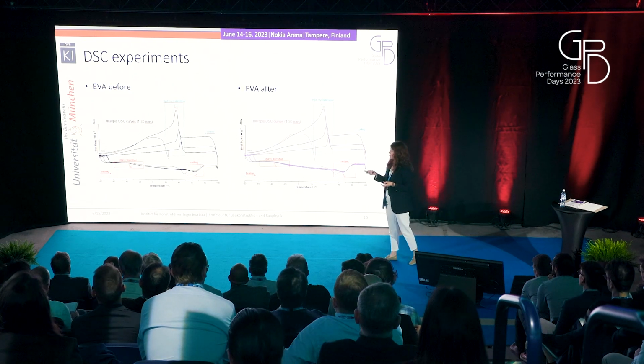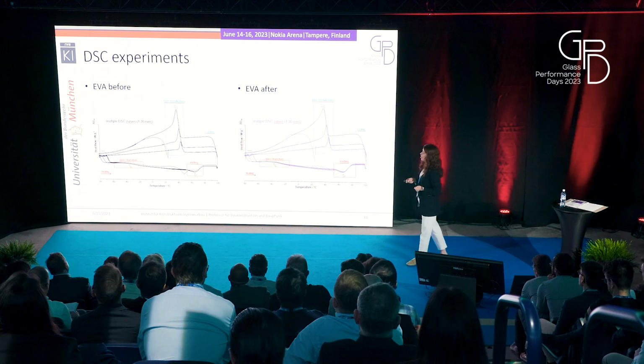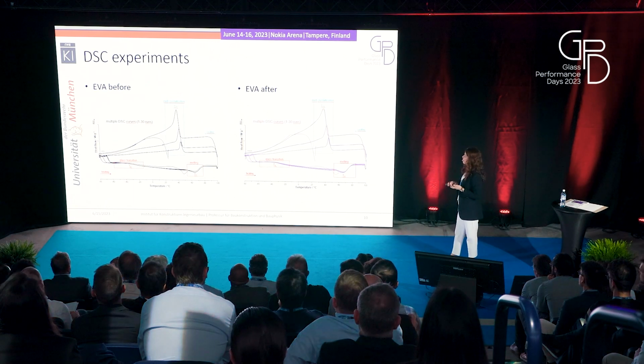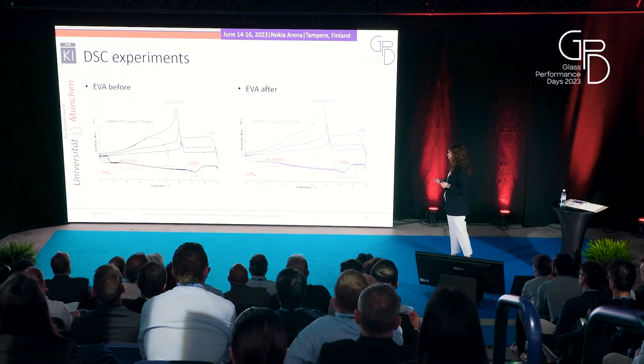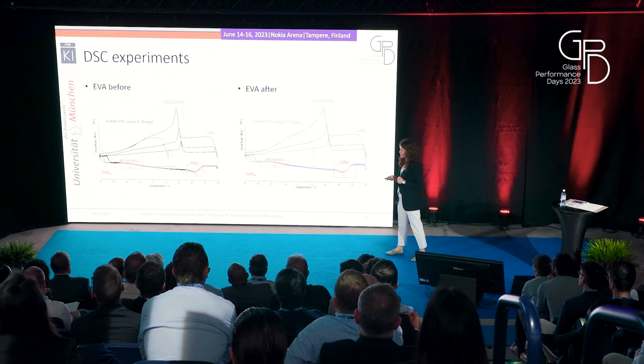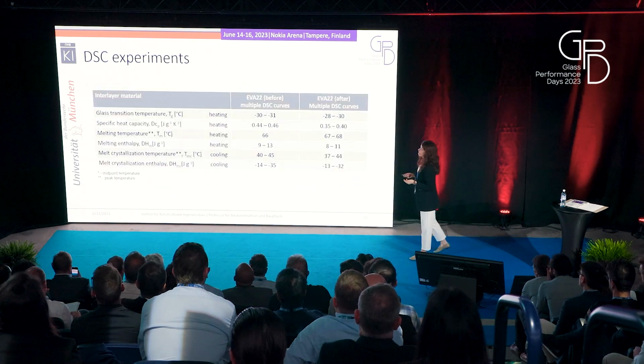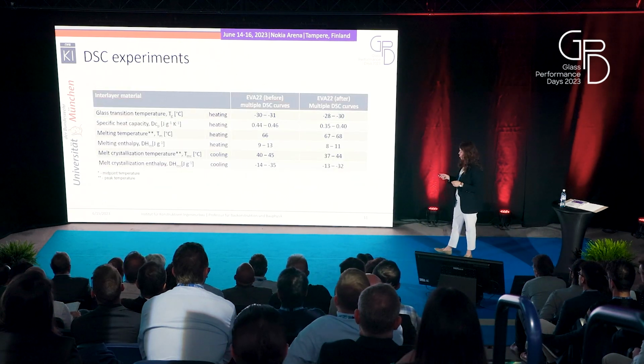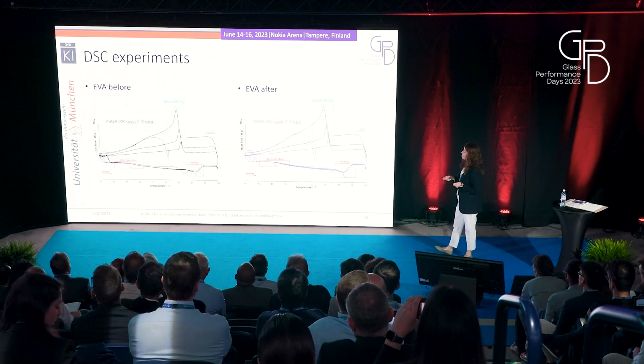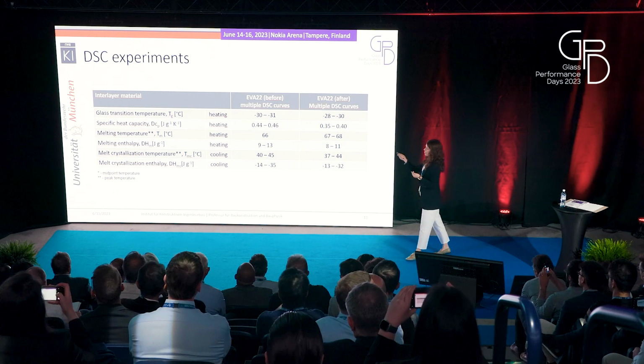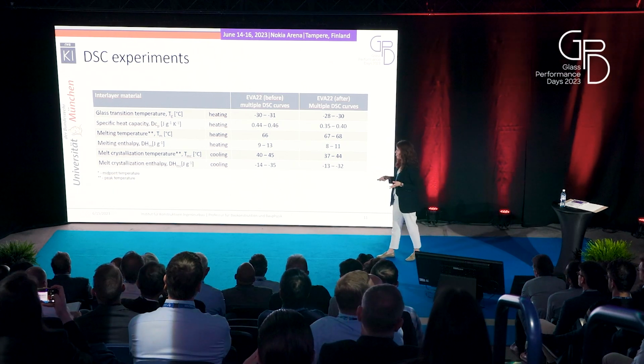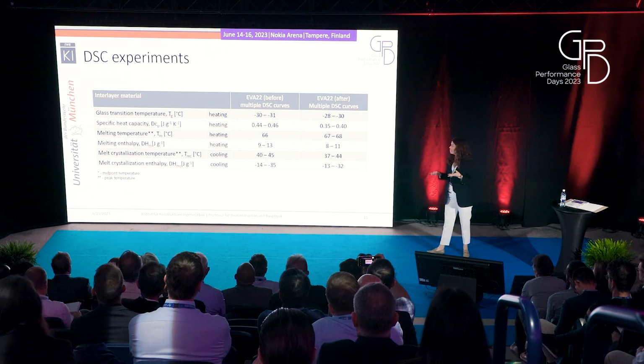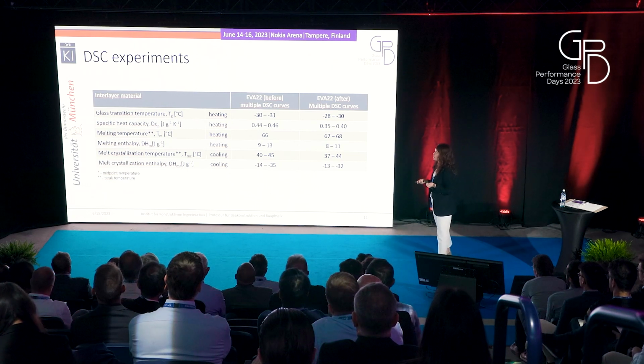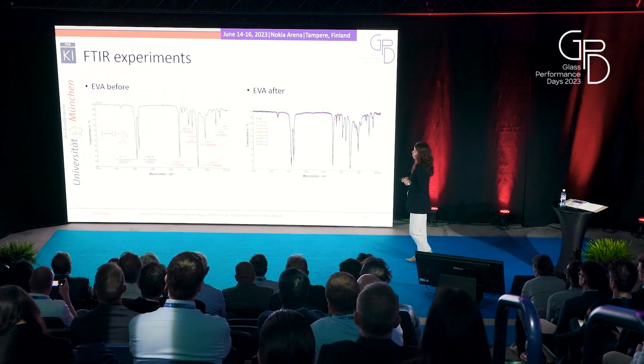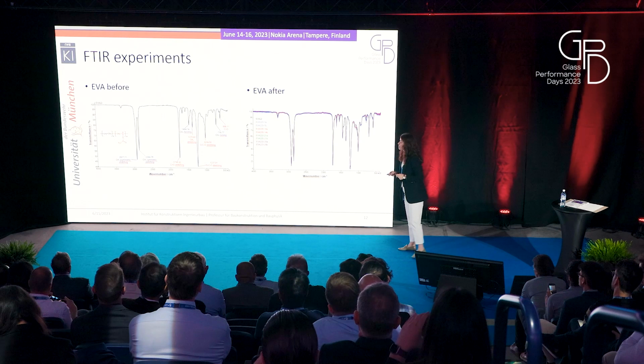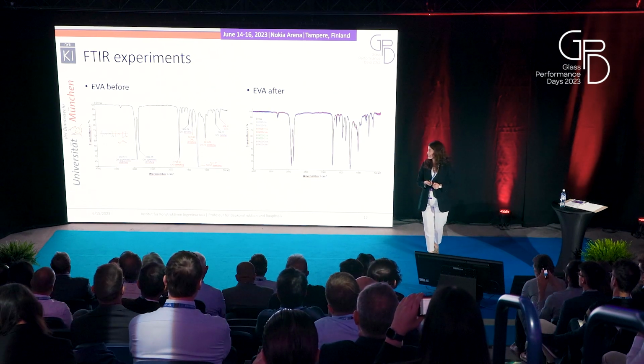So the glass transition, the crystallization phase, the melting phase. And just at a glance look of these diagrams, we can see that actually there's no big difference. Actually, there is a difference. Here is just a table of the diagrams that you just seen here. So there are differences when you look at the glass transition temperature. So there are some changes, but those changes can really, not that they can be neglected, but they are pretty small.